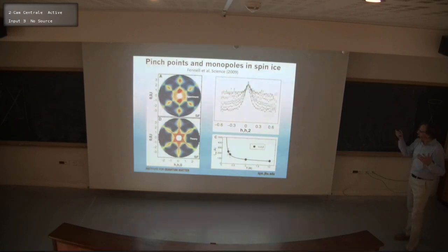Going off the charts is maybe a bit much to say, but it's getting pretty sharp, and it goes beyond 200 angstrom, actually. So you can say, what is that length scale? One way to describe it is that it's the distance between tetrahedra that violate the 2-in, 2-out condition. When you violate the condition, that's when you have effectively a monopole in that tetrahedron.